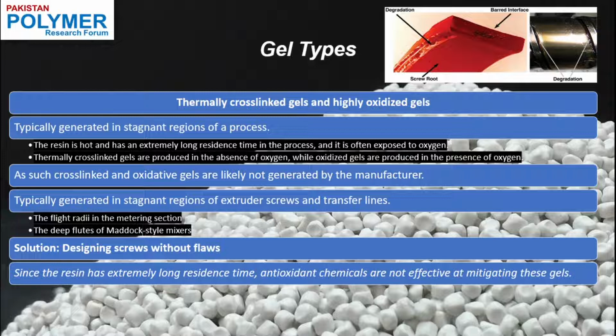To cope with these types of gels, it is recommended that the screw owner, who is the owner of the extruder, should request the rebuilder to maintain the flight radii size, especially for a first-time rebuild with a new fabricator. When the screw is returned to the plant after rebuilding, the screw should be inspected for flaws, including the flight radii, before the screw is placed into storage.